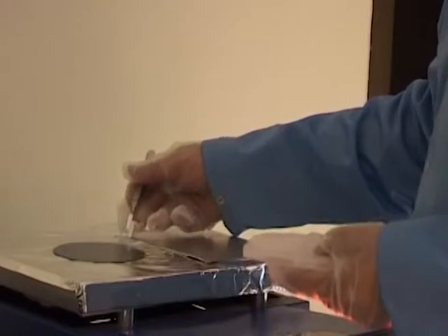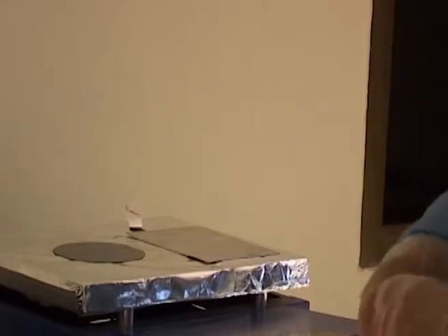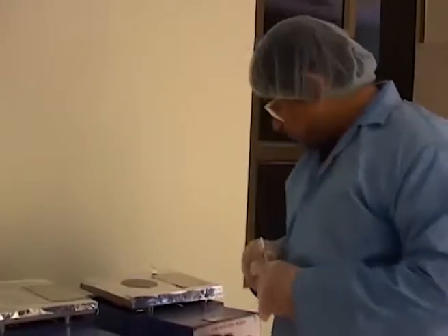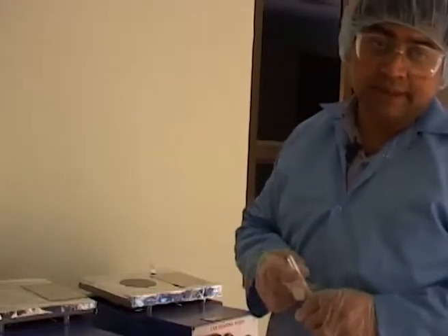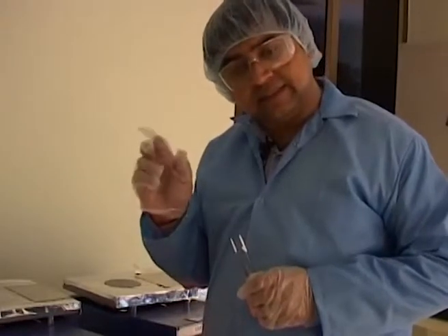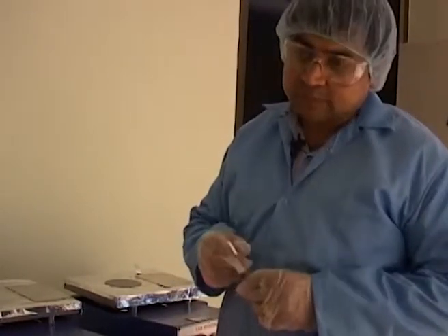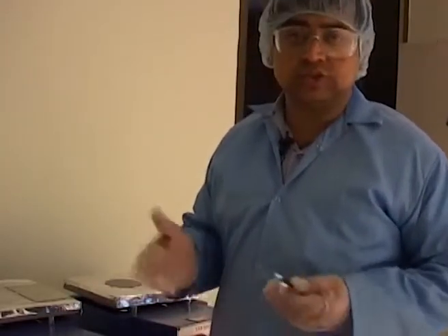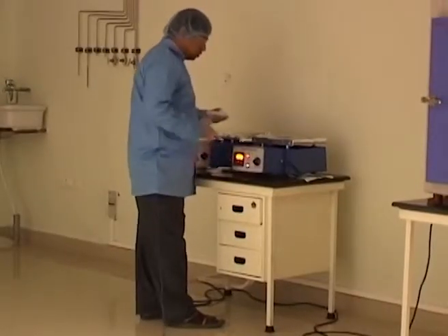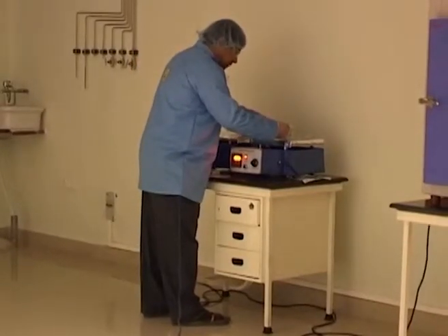Okay, so basically now we put it back onto this hot plate surface which is set at 95 degrees Celsius, and we heat this for about 6 minutes or so. One thing very good about this process is that if you look closely, you can really see the features coming up on the surface as you are heating at this 95 degrees. The points which are slightly mis-contrasted, you can see the different contrast there in the zone which is exposed. When you develop it using a developer solution, those are typically the zones which remain, and the remaining portions which were unexposed would go away, and that is what a negative tone resist is supposed to do on the wafer surface. So we are going to now pick up this wafer from this particular place.